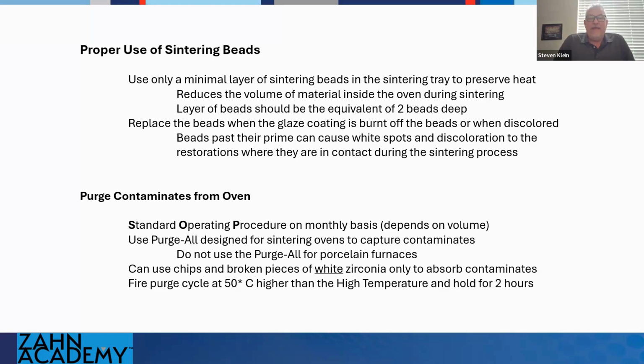As an alternative, you can use chips and broken pieces of white zirconia, though it must be white. Can't use a colored zirconia to mop up colorants. So if you do have some white zirconia around, you can take a hammer and break up the pieces and put a nice volume of that in the tray and fire it in that purging cycle. A lot of ovens do have purging cycles built into them, but a lot of them were designed prior to these more technical or higher temperature zirconias. So I would tell you to put in your own program.